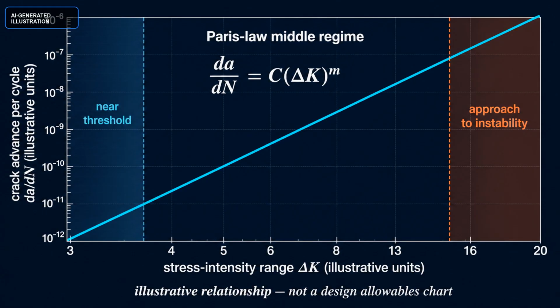In the middle, stable part of a fatigue growth test, engineers often use the Paris law, dA by dN equals C times delta K to the power m. dA by dN is crack advance per cycle. C and m come from material and test conditions. The important shape is not the letters, it is the exponent. If delta K rises, the advance per cycle rises faster than linearly. Early cycles may add almost nothing you can see. Later cycles add larger steps, even though the external load range is unchanged. Paris law is a regime model, not a universal promise. Near threshold, overload, variable amplitude, corrosion, short crack, and final fracture behavior need other evidence.